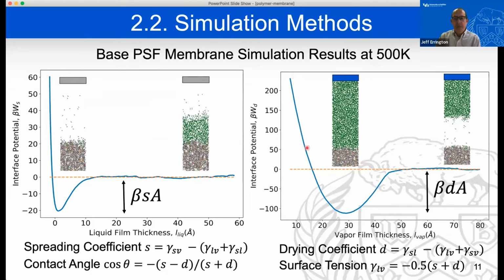So again, if you have a potential in which there's a minimum in it, that signifies that the system is in this partial wetting regime. And again, you can use the difference between the plateau region and the minimum in the potential to determine a key interfacial property. In this case, we refer to it as the drying coefficient. It's a different mix of the interfacial tensions between the solid liquid, liquid vapor, and solid vapor phases.